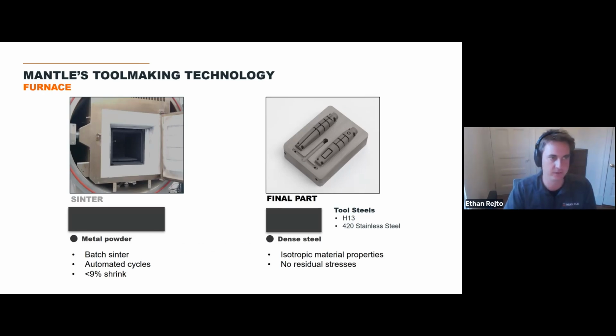After a part has been produced in the printer, it's going to go into a furnace. If you're familiar with metal injection molding or powdered metal processes, this is a sintering step. The part shrinks about 9% in the furnace, which is a lot less than most powdered metal processes, but it does shrink about 9% here. And that's the steel actually densifying and bonding together, where we're removing all the binder out of the part. There's no binder left in the part after this process. And the result is a dense, strong metal part with isotropic material properties and no residual stresses. So it's very, very stable.